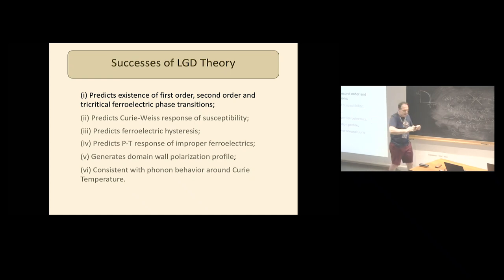In this case, instead of dealing with Q as the order parameter, let's call it like it is in a proper ferroelectric and call it P, where P is the polarization. Crucially, it's an order parameter, so it's not the polarization. It is the normalized polarization to the fully transformed low temperature, low symmetry state. So don't fall into that trap. P is just a number between 0 and 1, and it's going to substitute in here for what we had been using as Q.